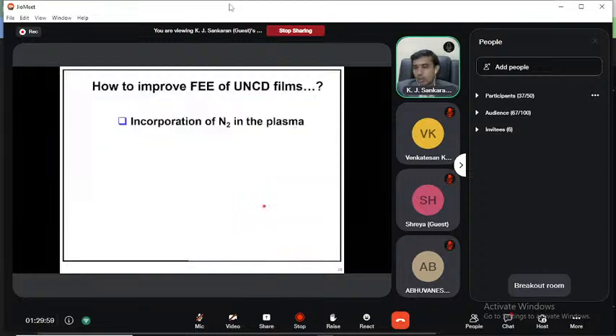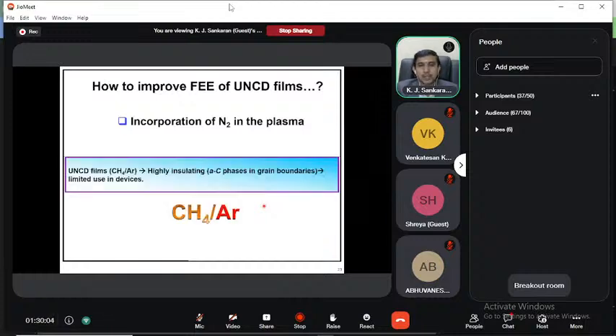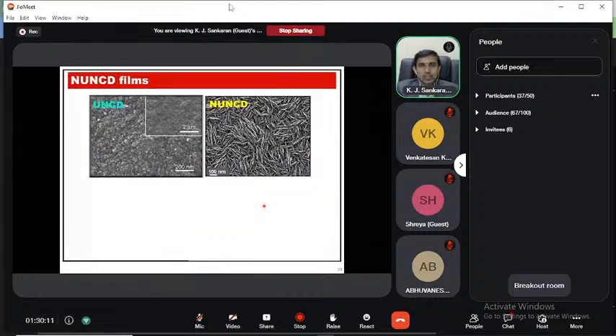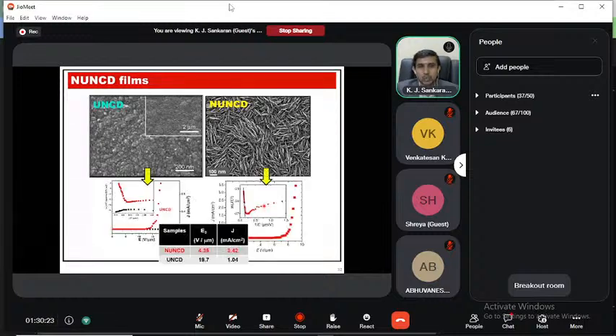Then we looked at the role of incorporating nitrogen in the plasma: we remove the argon and put nitrogen there. What happens to the morphology? You can see the UNCD grown in methane and argon has very small grains, but the nitrogen-incorporated UNCD has wire-like structures, which makes it a higher aspect ratio material than the UNCD. We measured the field electron emission properties. There you can see that the nitrogen-incorporated one has the lowest turn-on as compared to the UNCD, and with a high current density.